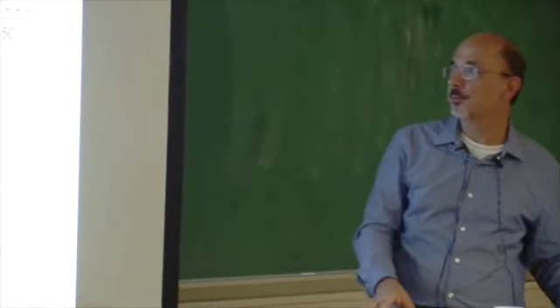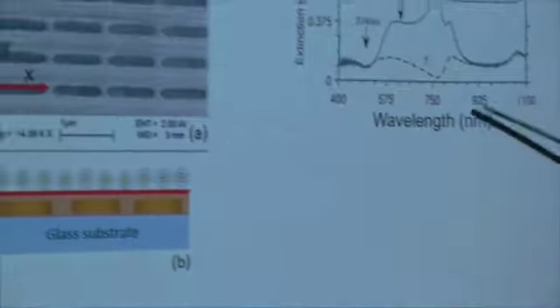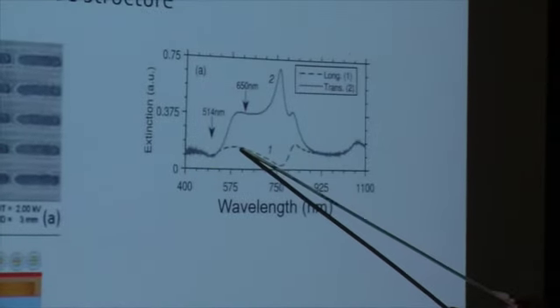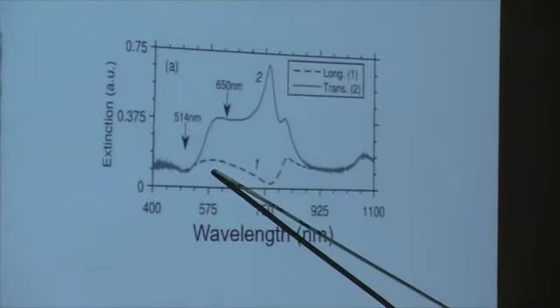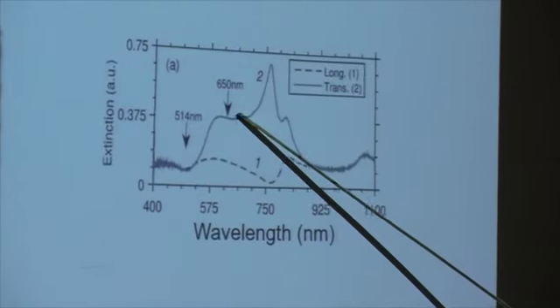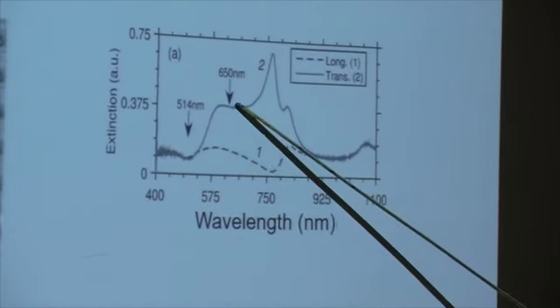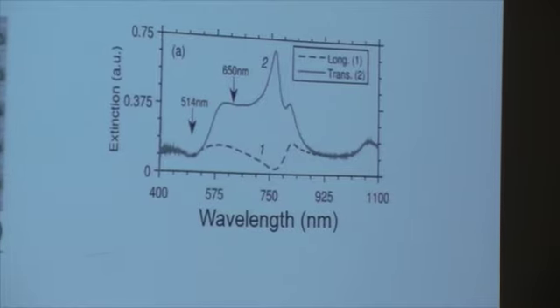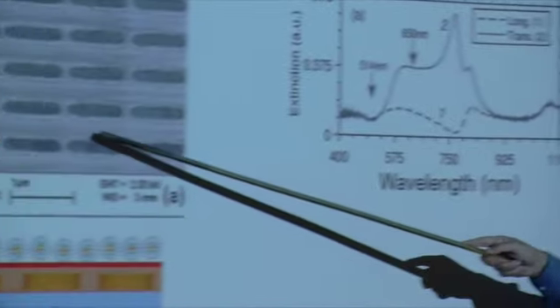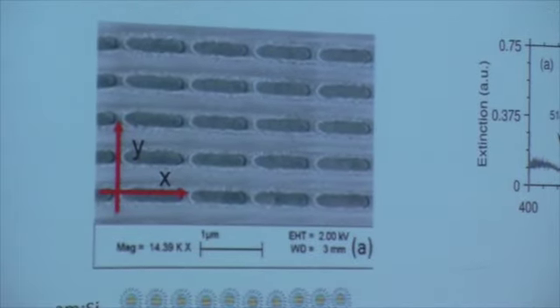If you look at this figure again, along the y-axis, there is not much going on. The plasmonic field is very weak. But along the x-axis, that one. X-axis, you have a pretty strong plasmonic field. So the quantum dot can couple with the metallic nanoparticle, and there is enhancement through the exciton-plasmonic coupling, but not exciton-plasmonic coupling that is generated by laser, but generated by the quantum dot itself.